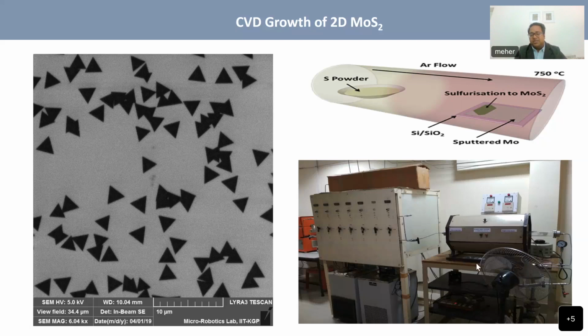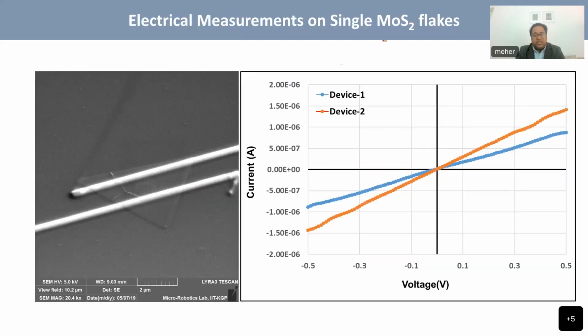So we prepared a different kind of chemical vapor deposition setup, and this is a two zone setup. If you want to heat the sulfur powder, you need one temperature, and if you want the reaction, you need a different reaction temperature. So you cannot have a single tube, single temperature furnace; you need a dual zone furnace. So we fabricated, actually assembled, a dual zone furnace in the lab at IIT Kharagpur.